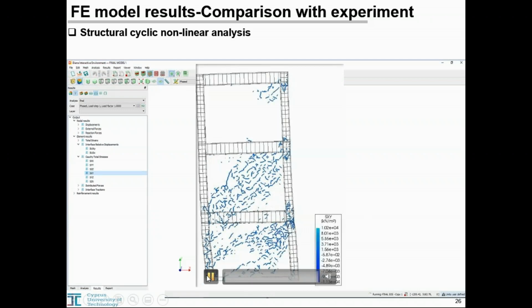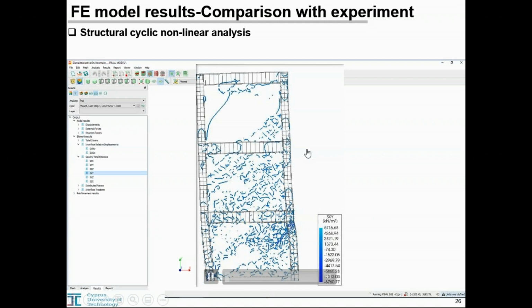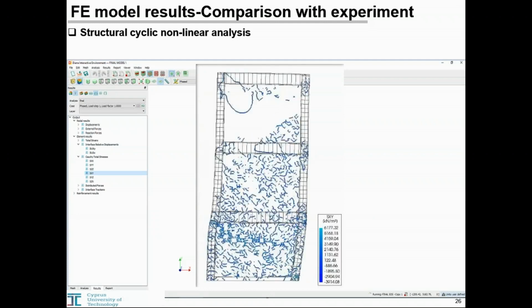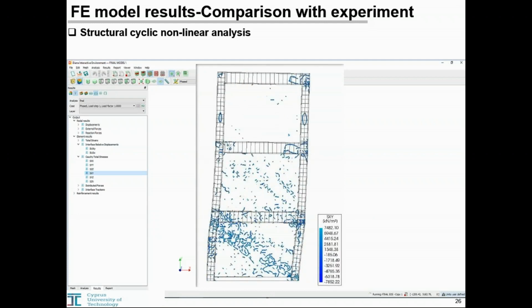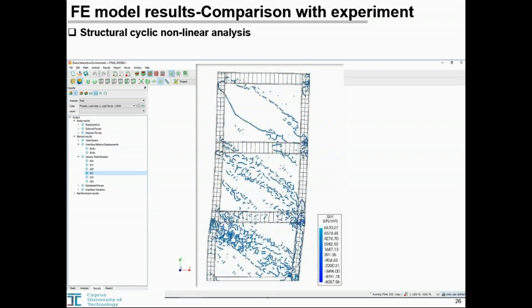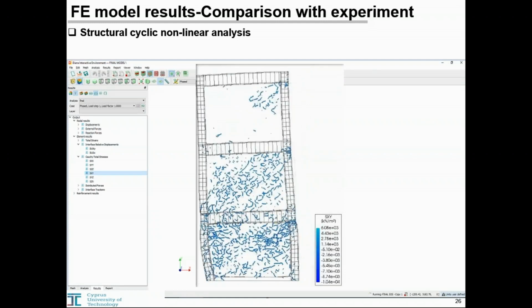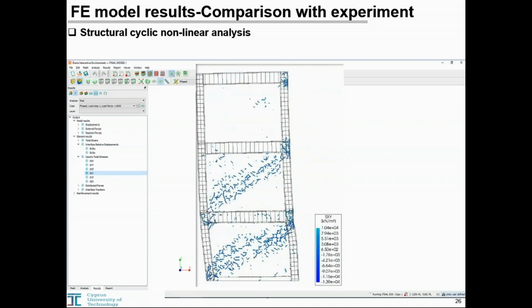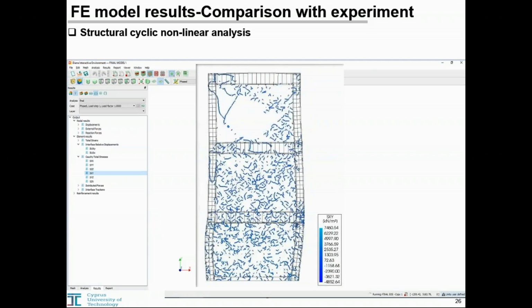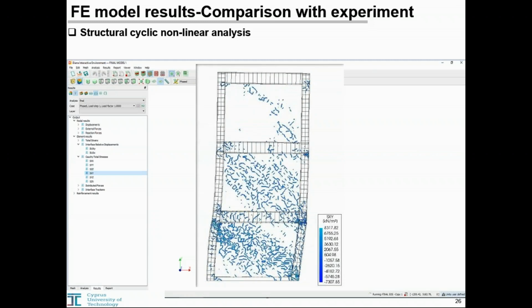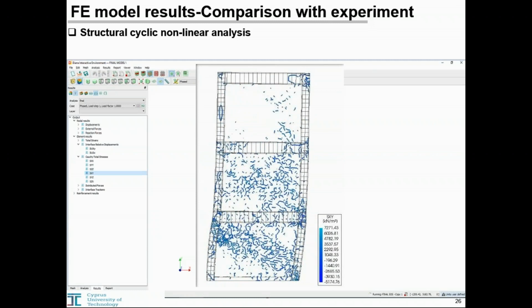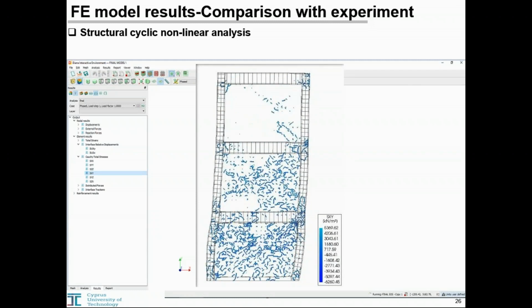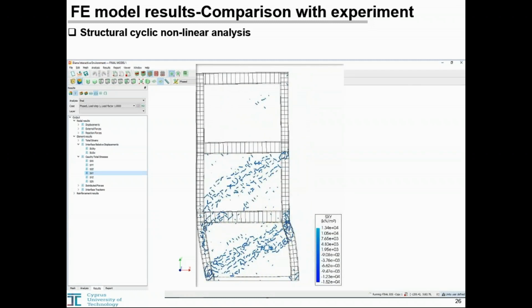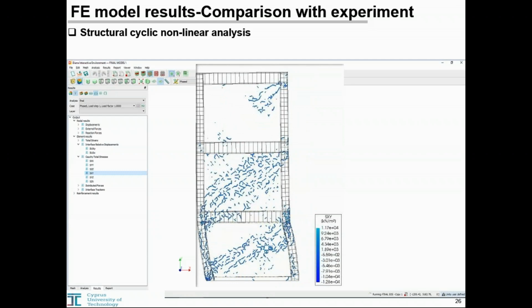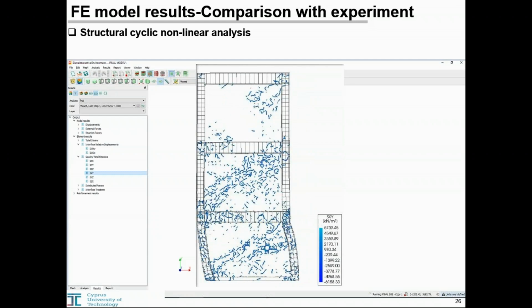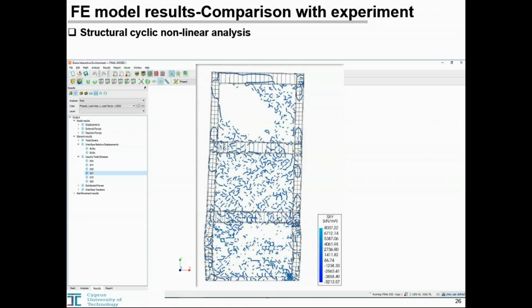Here you can see a small video, the evolution of the shear strength over the infill after the third cycle of loading. It is clear that the majority of the damage and energy is concentrated at the first floor. Also, you can see flexural horizontal cracks and tensile vertical cracks develop, which are reasonable for the beginning of the nonlinear behavior. You can see the diagonal strut, how it is developed.